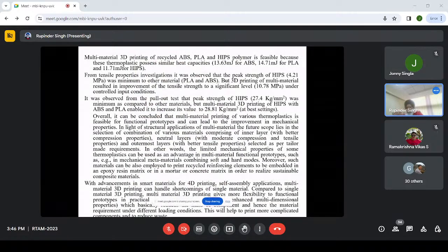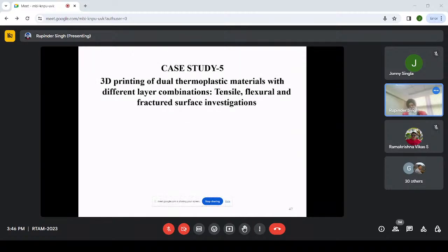So similarly with other things, we came to know which material we should print first, which material we should print later, so that I can have better control of the flow properties, and these were very much in line with the mechanical properties. Now, keeping these things in mind, we can actually tune the printing of the material. We can actually tune the crystallinity. We can actually tune the glass transition. We can plan the other thermal properties so that the best combination can be made.